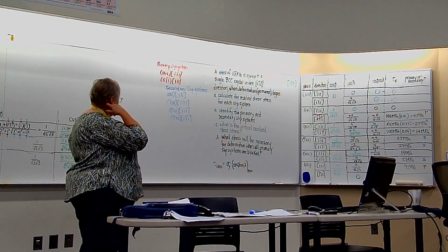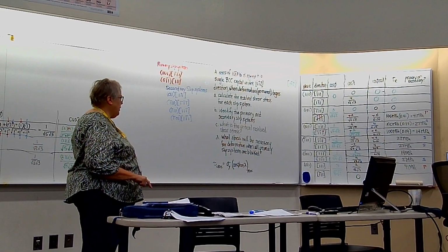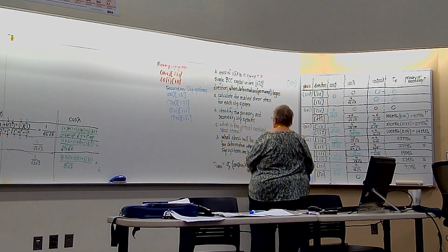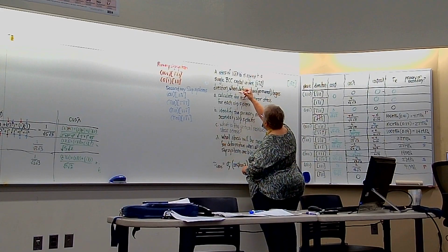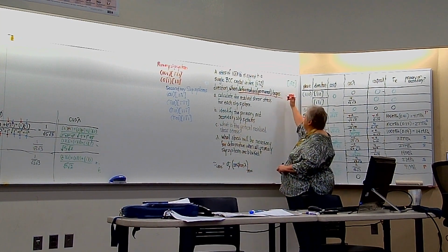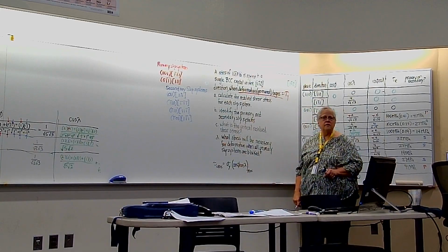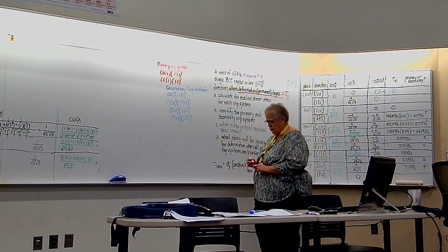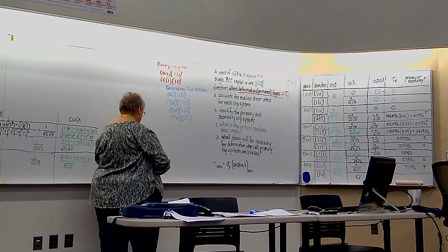Okay, the critical resolved shear stress is the yield strength times the maximum cosine phi cosine lambda. And we're told permanent deformation begins at 100 megapascals. That's the same as saying that is the yield strength. So the critical resolved shear stress here is our highest resolved shear stress.